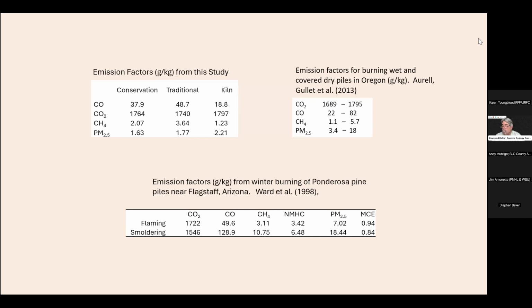Okay, so now let's compare the results we've gotten to other studies. There was a study conducted in 2013 looking at different types of pile burns in Oregon. And we can see the emission factors for those. As you can see, the results we got were kind of in the low range for CO and in sort of a mid-range for CO2, and for methane, kind of in the mid-range also. So kind of similar results. For PM 2.5, our results were lower than what were measured for those.